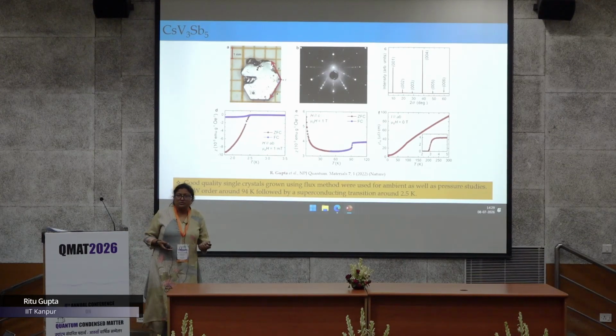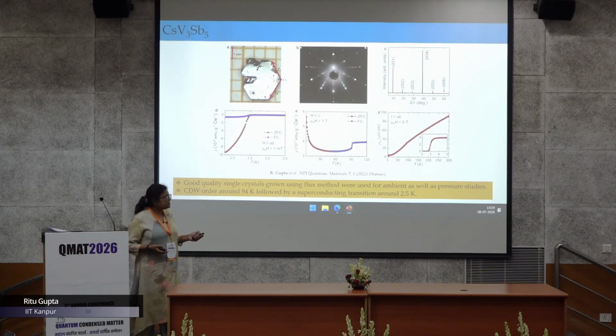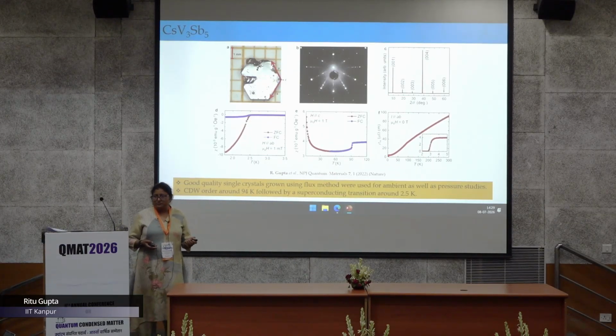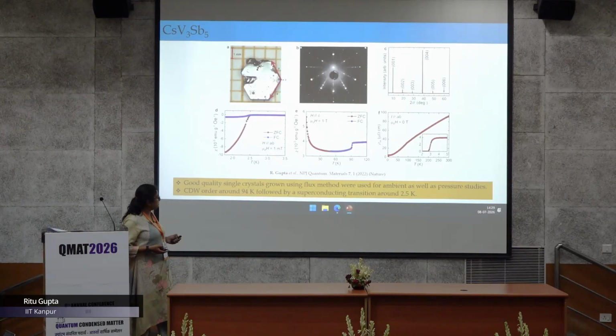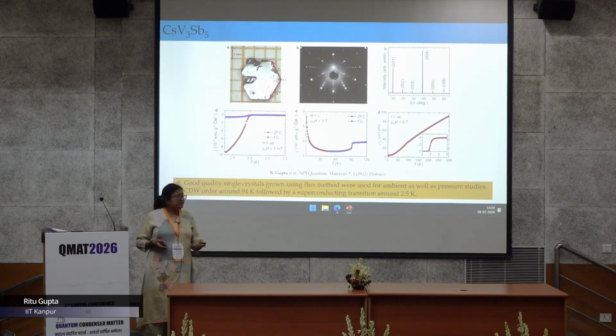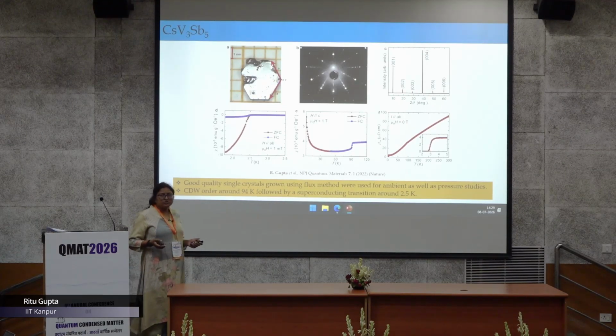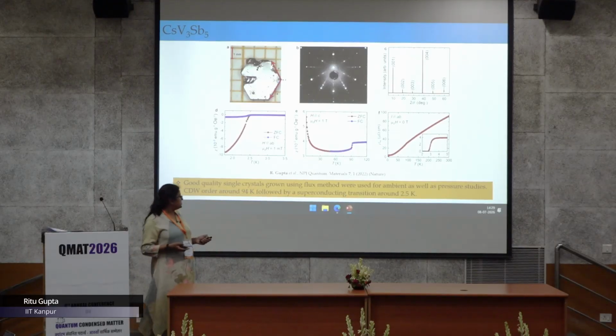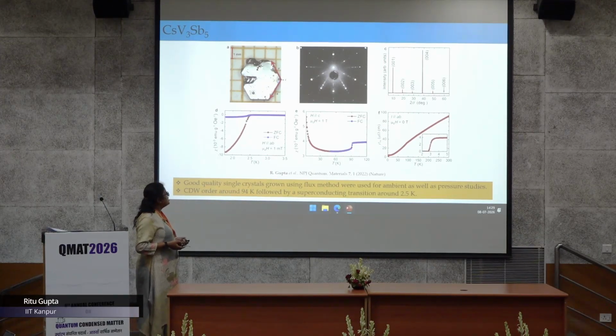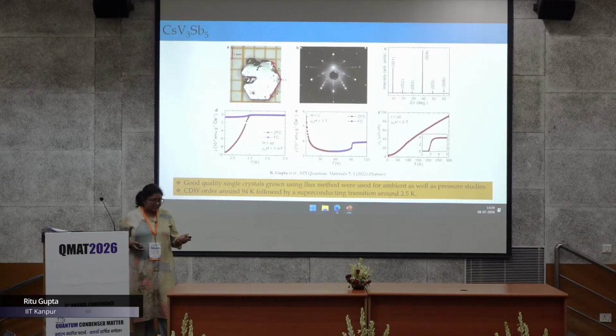Whenever the charge order phenomenon happens, there is a partial reduction in the density of states, and that is the reason for the decrease in the magnetic susceptibility and the kink in the resistivity. This is followed by a superconducting transition, which can be seen as a diamagnetic shift around 2.5 Kelvin, and a drop to zero in the resistivity, which happens at a slightly higher temperature, but that might be because of some filamentary channels present in the sample. So these well characterized samples were then used for the MUSR studies.